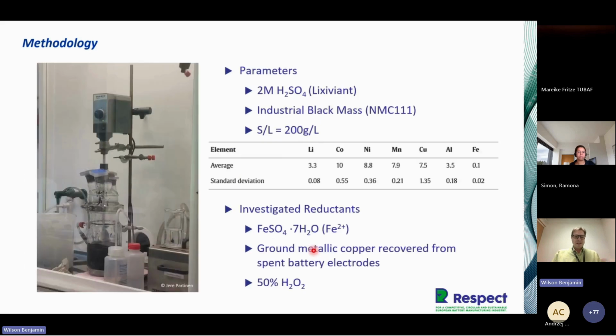So what does that look like in reality? Well, you can see it there on the left. There's some black mass in there, being leached by 2 molar sulfuric acid, our lixiviant. It's an industrial black mass from lithium-ion batteries, NMC111, so nickel, manganese, cobalt, all in relatively equal proportions. The critical thing that was mentioned as well is the solid-liquid ratio. The ratio we were using here was 200 grams per litre, which is more reflective of industrial levels of solid-to-liquid ratios.